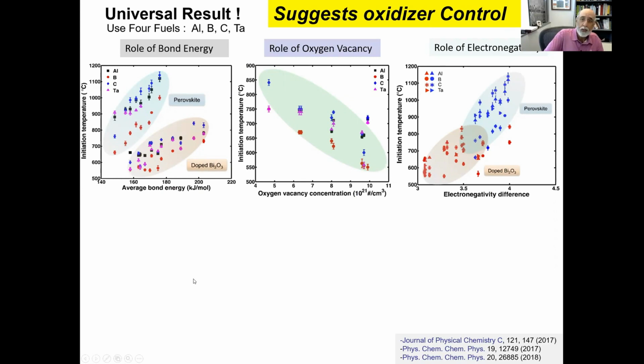And we can do the same thing with another class of materials. We did doped bismuth oxide, which we doped with other materials again to change their average bond energy. And so they show a different trend, different slope. They're lined up differently, but within a family, you see they do follow the same trend. And I can take all this data and look at the role of oxygen vacancy. You can see that as I increase the vacancies inside the crystal, places for oxygen to hop to, where there's an opening, there is a correlation that the more vacancies I put in, the easier it is to get the oxygen out, and the lower the ignition temperature is going to be.